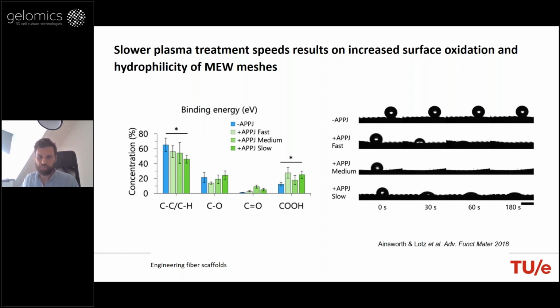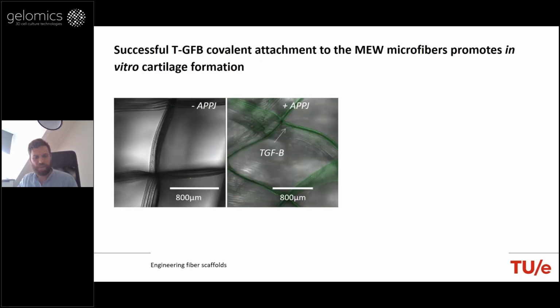What you can see here from XPS analysis and the water contact angle is that at the low to medium speeds, we could get more oxygen-containing groups present in the activated PCL meshes, and that led to a more hydrophilic surface. We then investigated the attachment of TGF-beta, and basically what we did was to soak these meshes in TGF-beta containing media, and then we washed the mesh with detergent. So if the growth factor was not covalently attached to the mesh, it was basically being washed out. And then we stained after this detergent wash to see if the TGF-beta was present or not. And to our surprise, we saw that, as you see here, stained in green using immunofluorescent staining for TGF-beta, the plasma-activated meshes were able to covalently attach the TGF-beta.